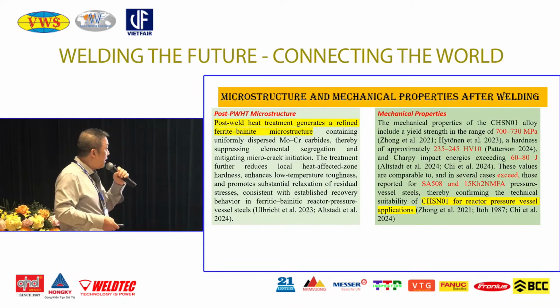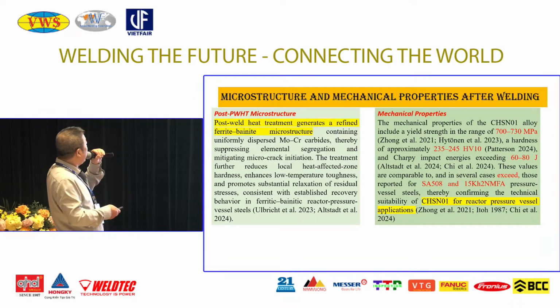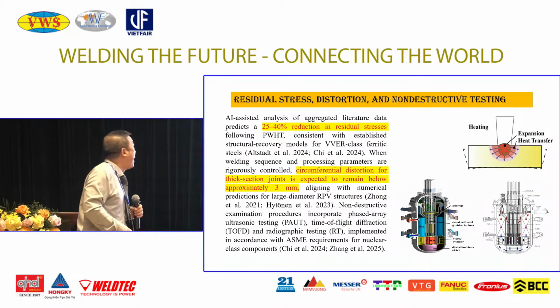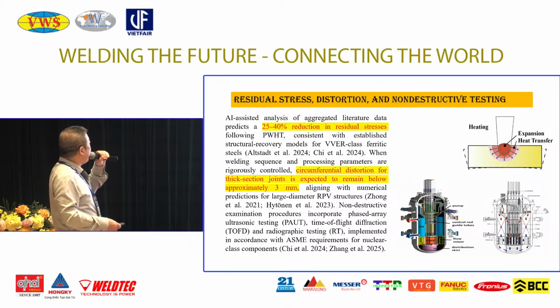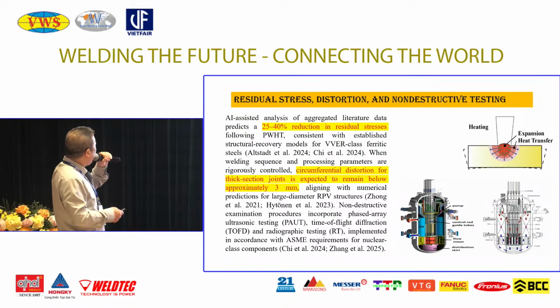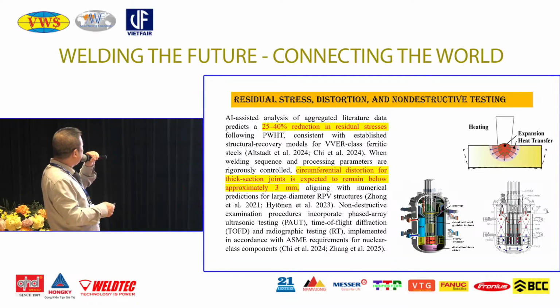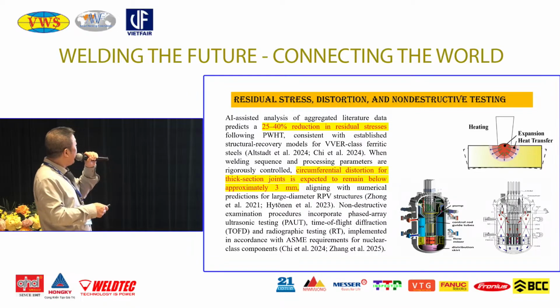About the microstructure, we also use post-weld microstructure analysis and mechanical property testing. In the final result, AI-assisted analysis of aggregated literature data predicts about a 25 to 40% reduction in residual stresses following post-weld processing. And circumferential distortion for thick section joints is expected to remain below approximately 3 millimeters.